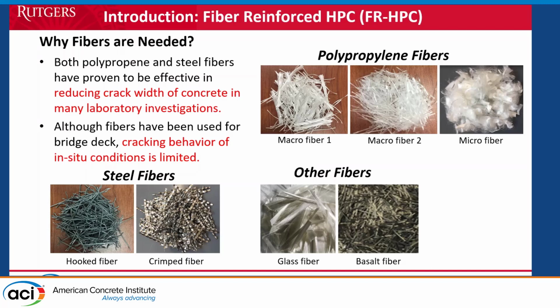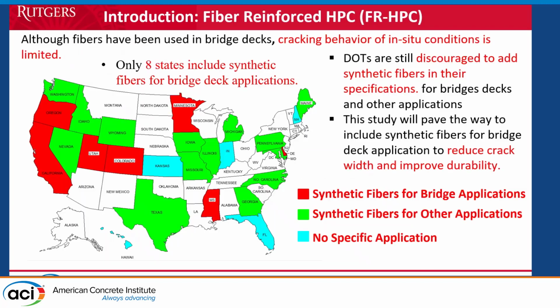So some of the fibers that we have used were steel fibers, which I think the producers or the contractors in general were totally not happy with. It's very hard to work with, so you need to have a special volume fraction to make it more workable. And we also used synthetic fibers, polypropylene fibers, and the macrofibers and the microfibers. We use different lengths of fibers for these synthetic fibers. And we use different fibers from different producers, so in the specification when we write it, we don't want to bias it to one producer of the fiber.